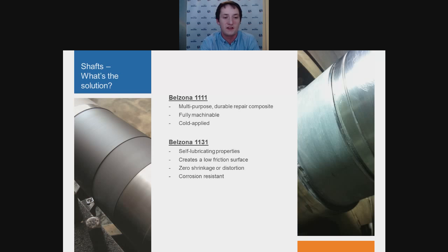Again, it's a paste grade material that can be applied in situ to rebuild the shaft. But this one has self-lubricating properties, so it's got a very low friction surface should that be required for the service. Then the final material we've got here is Belzona 1321.